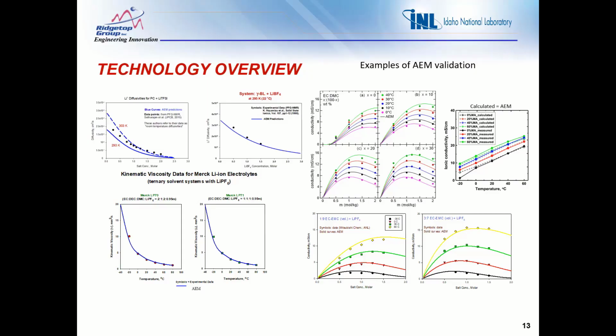As we go to the right, we see examples of conductivity predicted for different cases of methyl acetate with or without EC-DMC. This study was done with Jeff Dahn's group out of Dalhousie University, and we saw very good agreement with their data. Then at the bottom right, we have conductivity for the EC-EMC LiPF6 system that originated out of Oak Ridge National Laboratory. And at the bottom left, we have viscosity predictions: the data is from Merck Corporation and the predictions are by AEM.